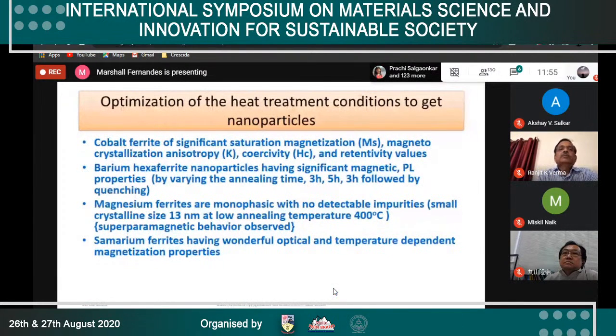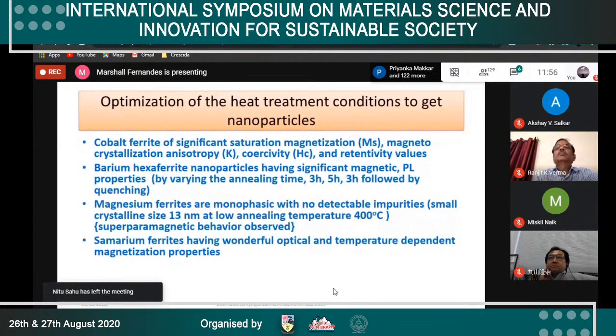The important properties found, for example, in cobalt ferrite prepared by the citrate precursor method: cobalt ferrite of significant saturation magnetization, magnetocrystalline anisotropy, coercivity, and retentivity values were obtained. And similarly, barium hexaferrite, which is otherwise very hard and difficult to prepare, could be prepared by the citrate precursor method in a convenient way at low temperature, giving very interesting nanoparticles having significant magnetic and photoluminescence properties.